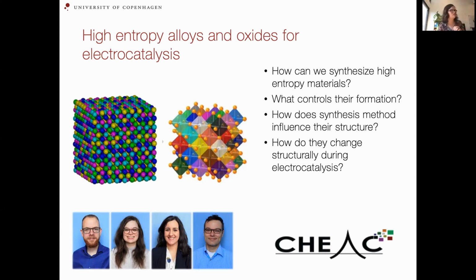So this is a metal, right? So an FCC, and you can put a lot of different metals on the sites. In an oxide, you do the same, but just in an oxide structure. And in CHEAC, my group in particular, or in collaboration with these in my group, we study how we can synthesize high entropy materials, what controls their formation, and how the synthesis method influences structure. So a lot of the same themes that we've seen in the examples so far.